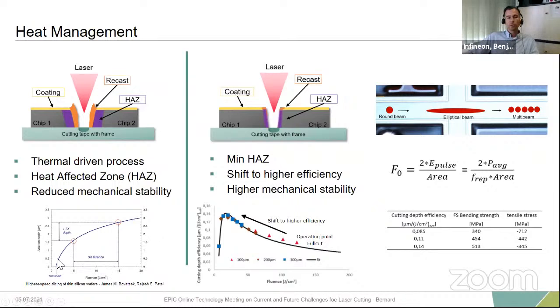The fluence and your cutting depths don't scale linear, they're logarithmic. That means if you put 3 times more fluence, then you're not cutting 3 times deeper, but you have kind of an efficiency loss. And we laser engineers consider cutting efficiency as the depth that we reached divided through the energy that we had to spend on a certain area. And if you see that, it's clear that your sweet spot for machining is usually at lower fluences.